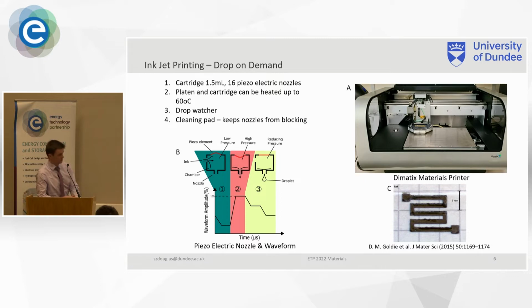It's important to control that so that we don't get satellite droplets behind the main droplet, as that will cause splashing on the deposit, which can cause defects. On the bottom right, there's just a demonstration of a complex structure that we can print with the printer, with the platinum ink as well.